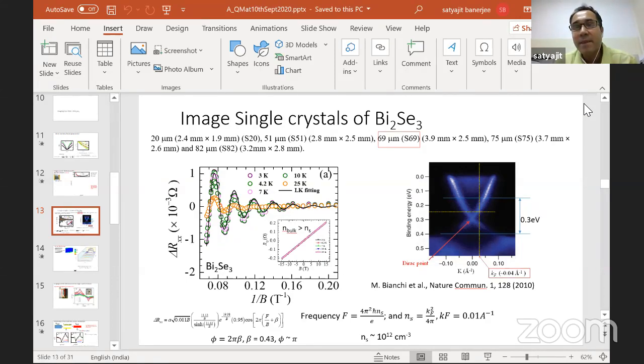Okay. So, Satyajit, I have just a very small question related to the vacancy concentration. Has it been calculated in the literature how much is the typical selenium vacancy concentration? I think they have done positron annihilation studies on these crystals, and 10 raised to 13 or 14 per centimeter cube, something of that order. Yeah, but that's quite low actually. I am just quoting out of my head. It could be slightly higher, but it will be 14, 15, I think. Okay, thank you. So thanks for this very interesting talk, Satyajit.